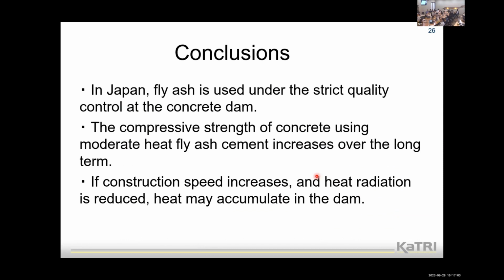So that's the conclusion of my presentation. In Japan, fly ash is used under strictly controlled conditions at concrete dams. And the compressive strength of concrete using moderate heat fly ash cement increases over the long term. This is most likely known to all of you, I think. But if construction speed increases and heat radiation is reduced, heat may accumulate in the dam. So that's the end of my presentation. Thank you for your attention.